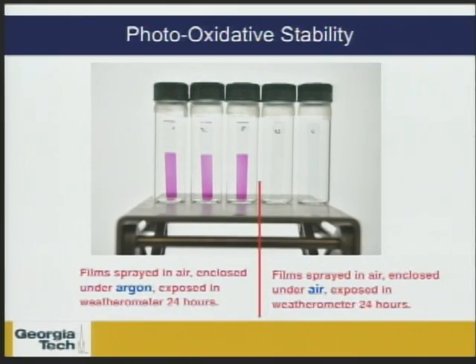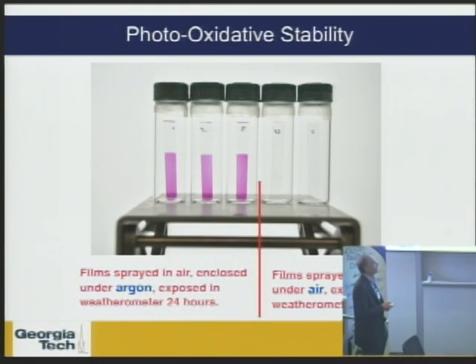And I think the last piece of information I want to talk about is this very recent experiment that was done that has to do with the photo-oxidative stability of this ECP-Magenta polymer. What was done here is these 5 samples were sprayed onto ITO glass or glass, I don't remember right now, and they were placed into containers either in air on the right-hand side or argon on the left-hand side. And then they were irradiated in a weatherometer for 24 hours.